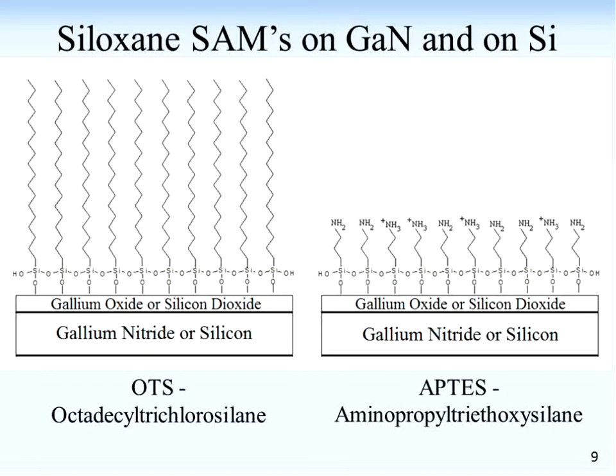When it comes to silanes, they have a high affinity for oxide surfaces, and there's an actual chemical reaction that takes place. There are a wide variety of well-known surface molecules and combinations, but I focused in on this silane chemistry. What happens is surfaces that have a native oxide — the silane is going to form a stable siloxane bond. This is a silicon-oxygen bond between the silicon head group on the SAM and the oxide surface, and this bond is very stable and very strong. A lot of my work involves using either silicon surfaces or gallium nitride, which is a type of 3-5 semiconductor surface. I've had a lot of SAMs on GaN — and if anyone's a fan of Dr. Seuss, you know the book Green Eggs and Ham, you can imagine I've had a lot of jokes about SAM on GaN.